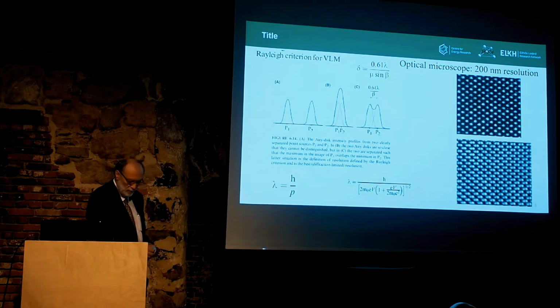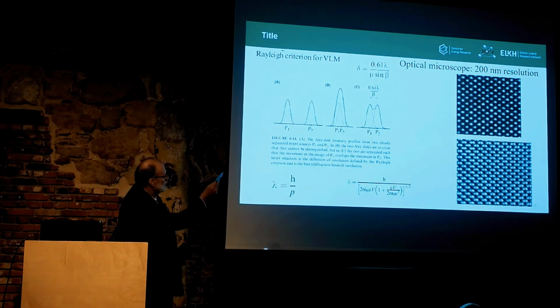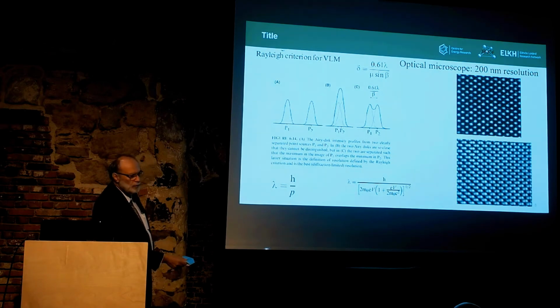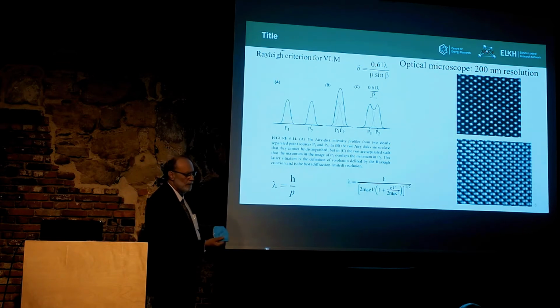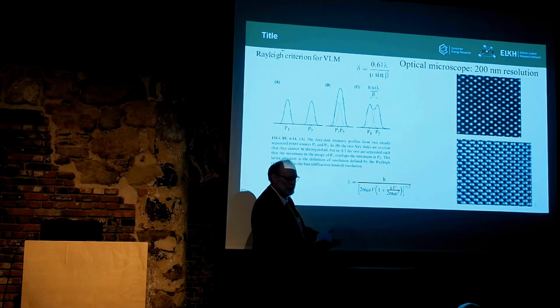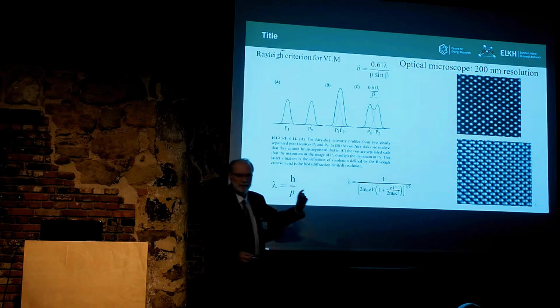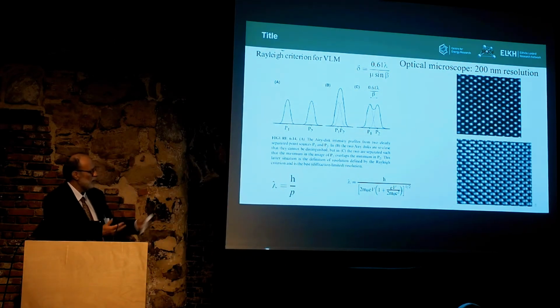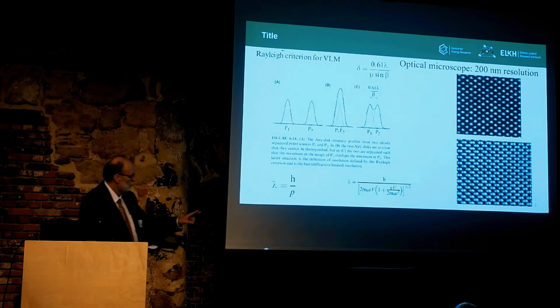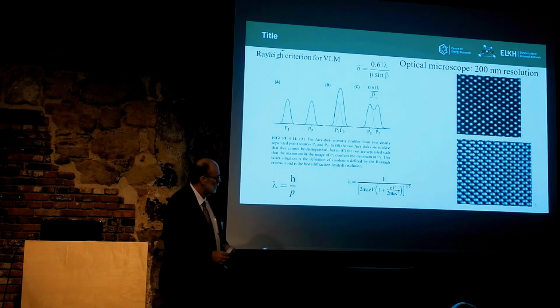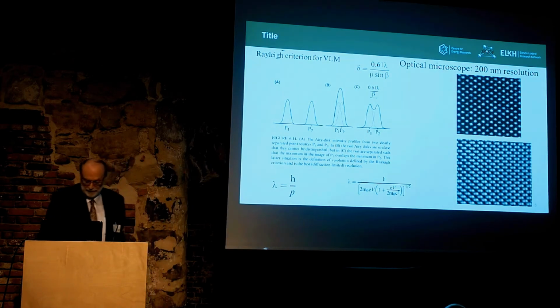And those two images, both of which I took in a transmission electron microscope, are images of single crystalline diamond with very small spacings. The largest spacing between the atomic rows is about 0.2 nanometer, 2 angstroms. There is a big difference. This one is taken in our new microscope, which we purchased 3 years ago. And because we have very good resolution, it turns out that above, there are two carbon atoms behind one spot. We needed a better microscope and new principles to resolve them, because the very short distance between them is 89 picometers, so below one angstrom.